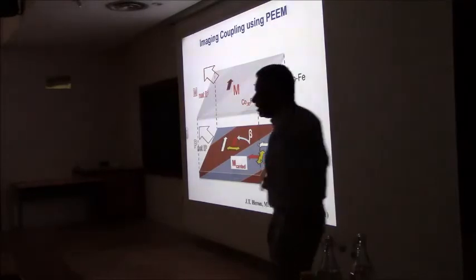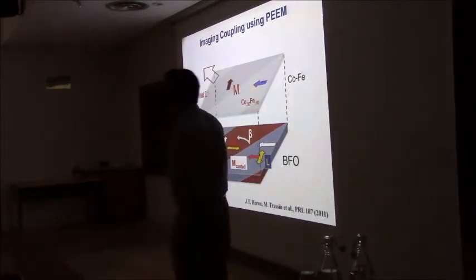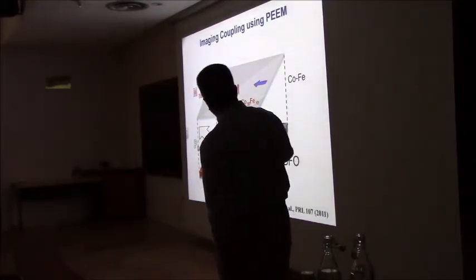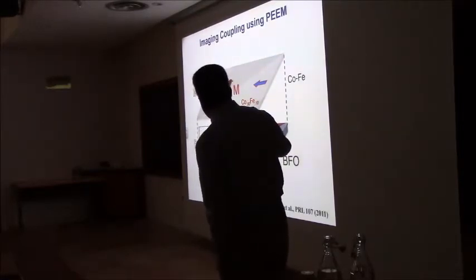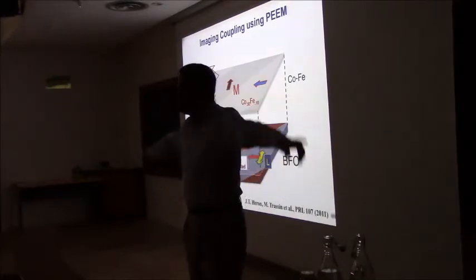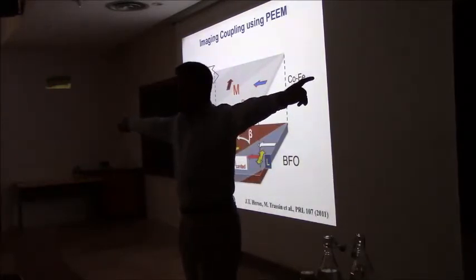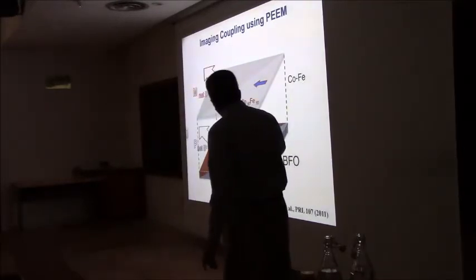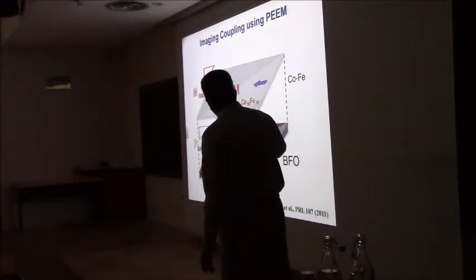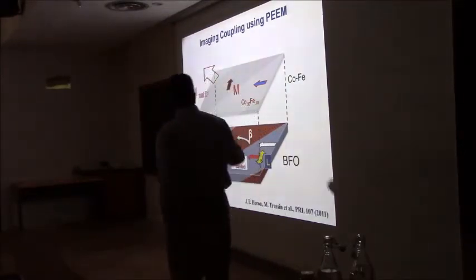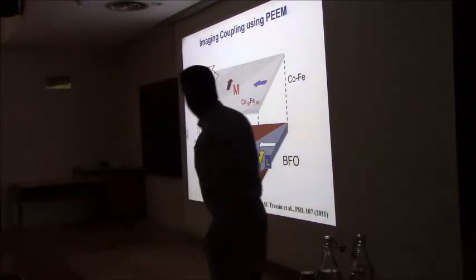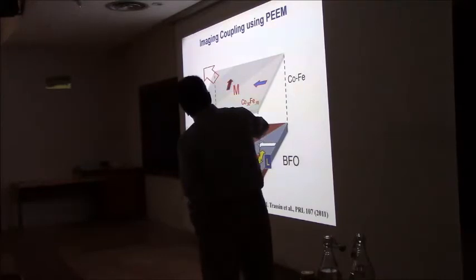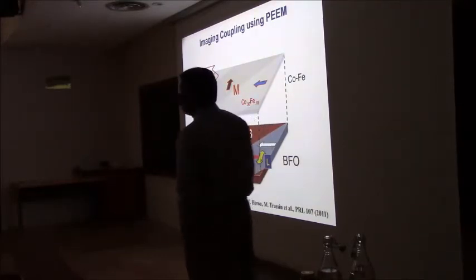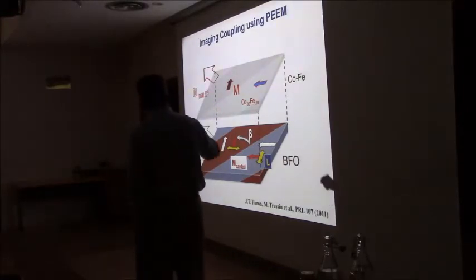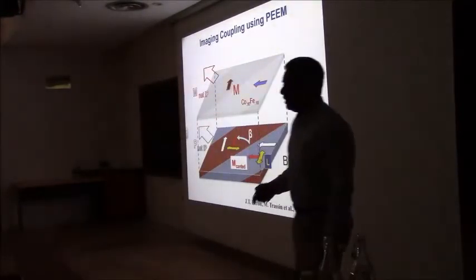So I can summarize the coupling between a ferromagnet, in this case a very canonical ferromagnet, cobalt iron, and the bismuth ferrite at the bottom, like so. These are the domains that we talked about. The projection of the polarization is like so. So what looks like 71-degree domains is actually projecting as 90 degrees on the 100 surface. The projection of the canted moment is also 90 degrees, and the yellow is the antiferromagnetic cell vector. This is what we know, or we think we know, about the canted moment. So there's a net in-plane moment in the ferromagnet pointing this way. So the question we're asking is, if I switch this by 180, will this switch? And I'm going to show you some data which says, yeah, very likely it does.